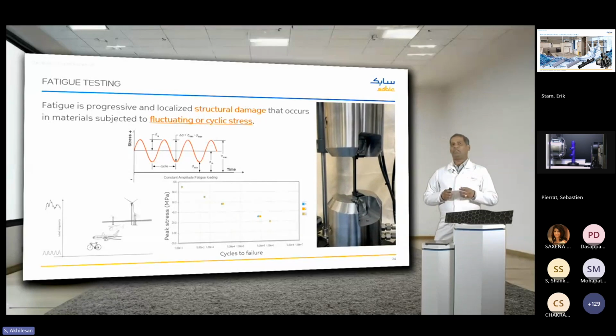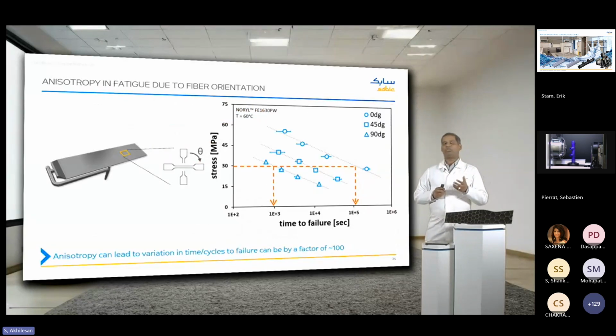Now let's take a look at why anisotropy is very important when it comes to fatigue in fiber-filled materials. Shown here is a graph of fatigue data for specimens that have been cut from plaques in 3 different directions, 0, 45, and 90. As with the tensile bars, we see that the fatigue properties in the 0-degree orientation provide the highest performance, while that at 90-degree orientation provides the lowest performance.